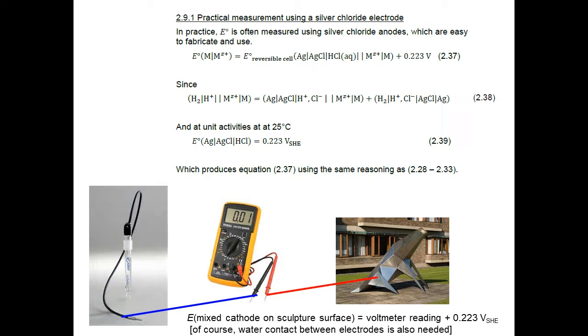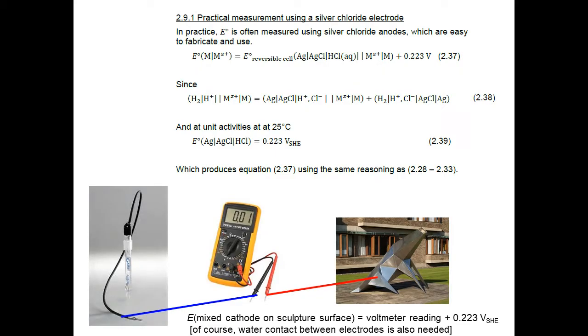So those measurements are done in practice using not a standard hydrogen electrode as our reference from which to measure, but instead typically using something like a silver chloride electrode, which is much easier to manufacture. It's just a silver wire which has been put in some hydrochloric acid for a bit, and then that's it. You can just stab that into the ground and that's your reference electrode.